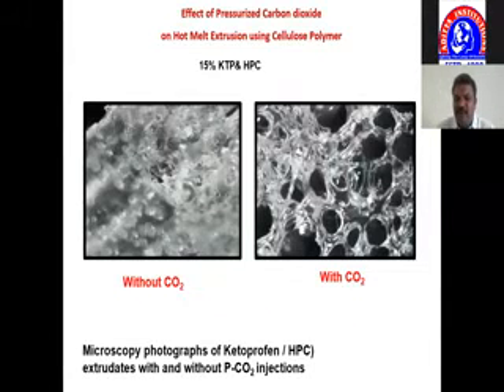Now, same ketoprofen and HPC, when you run this process without carbon dioxide and with carbon dioxide, once the extrudate comes out of the barrel, these are cross-section micrographs of the extrudates. Without carbon dioxide, what you see is there is no porous structure over here. But with carbon dioxide, what you can see is a nice porous structure which has been formed. Because the moment the material comes out, there is an expansion of the gas. Once the gas expands, it leaves a porous structure behind. So this is the porous structure of the extrudates when it comes out of the hot melt extrusion with carbon dioxide.